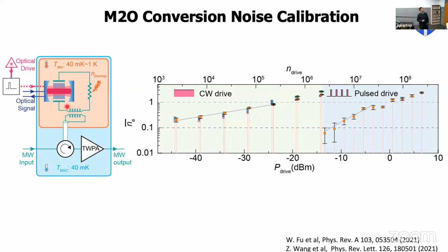We just use a temperature variable stage to support this microwave to optic converter. We vary the temperature from 40 millikelvin to 1 Kelvin. Basically we create a black body source together with a conversion signal. This black body source can be quantified with very efficient readout circuits. This quantum limited traveling wave amplifier can read out the thermal photon with the calibration provided by the black body radiation. And we can also reach about 0.03 imprecision of measurement of the thermal occupation of a microwave mode.